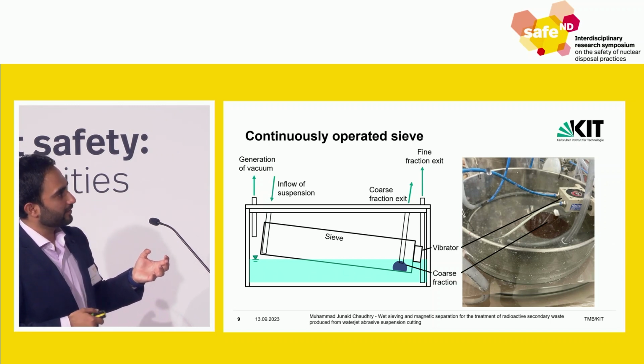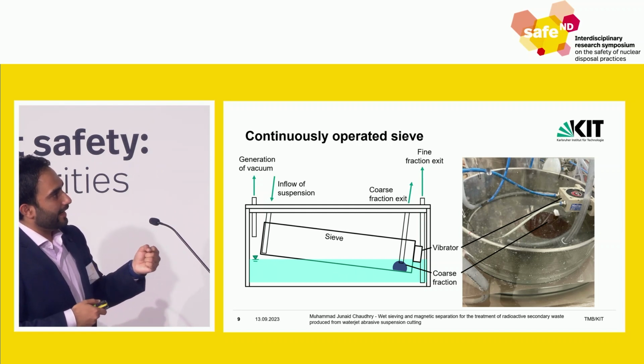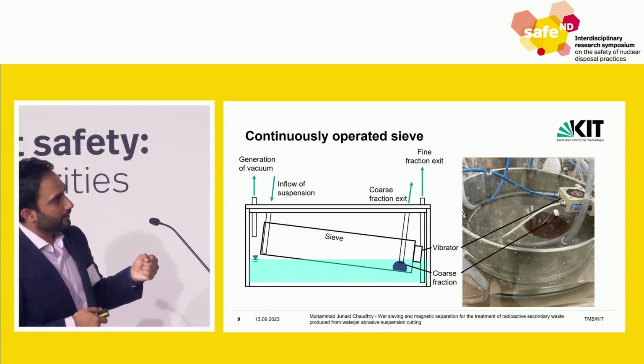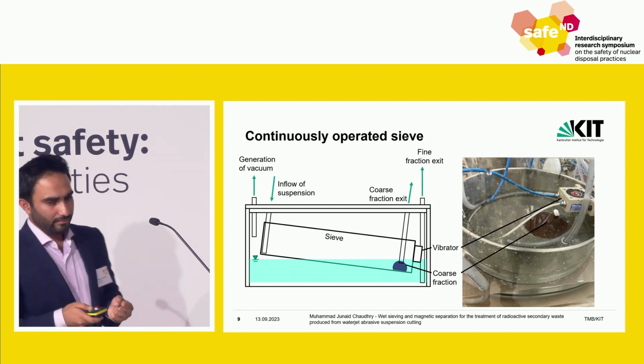As the sieve is equipped with a vibrator and is halfly under water, the particles move towards this point, and the fine particles just move in the water. The coarse fraction is taken out by the coarse fraction pump, and the fine fraction can be pumped by the other pump.